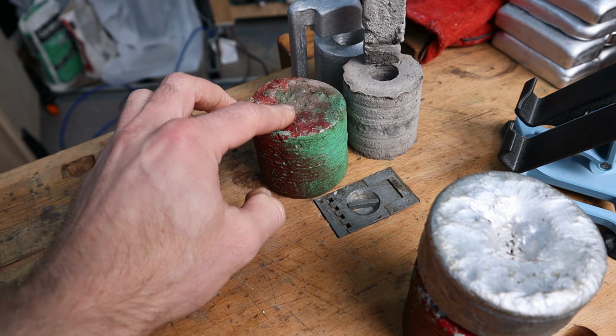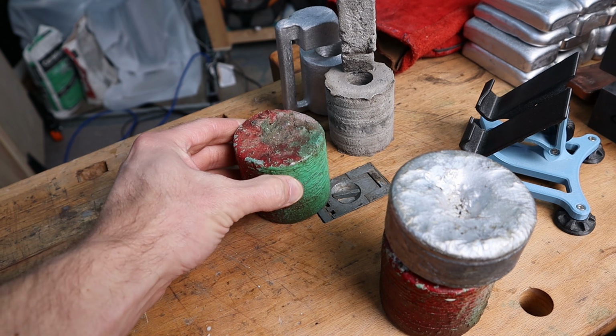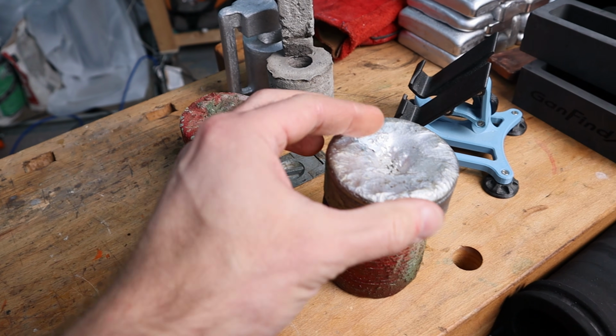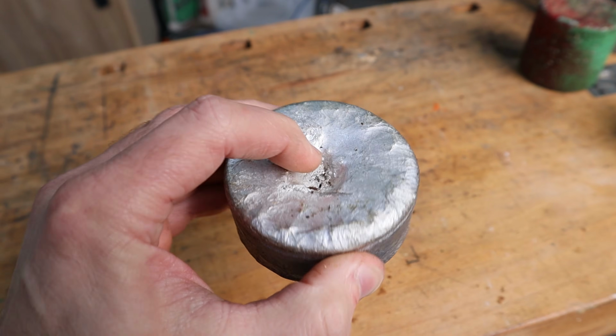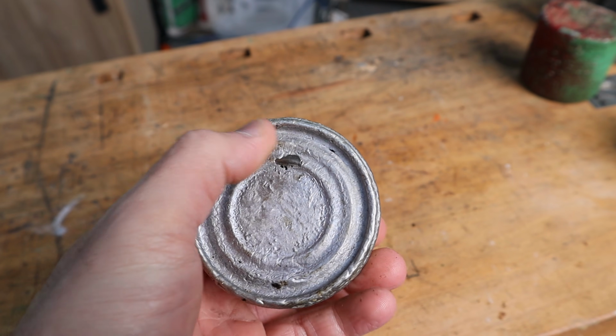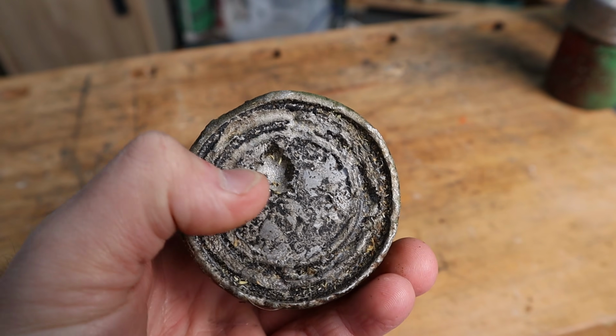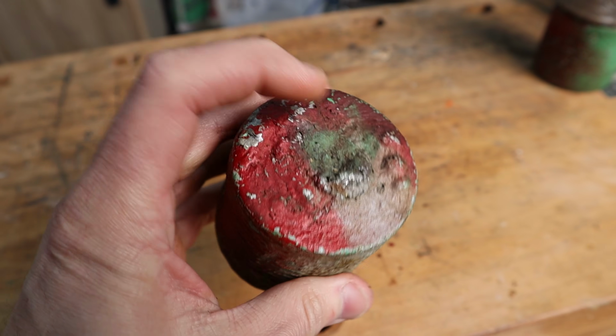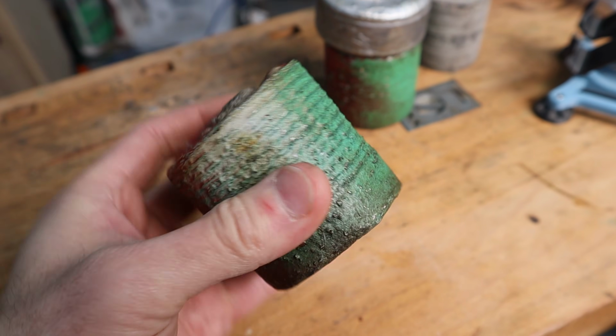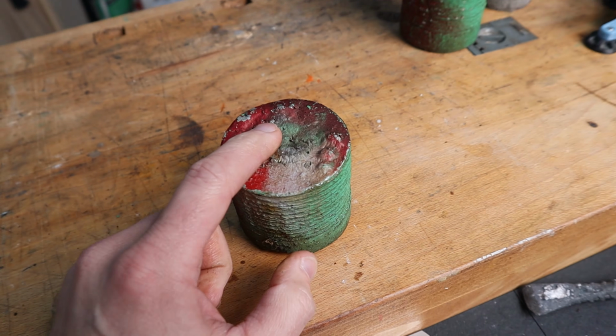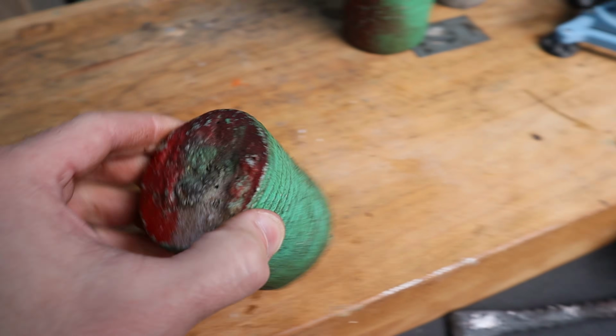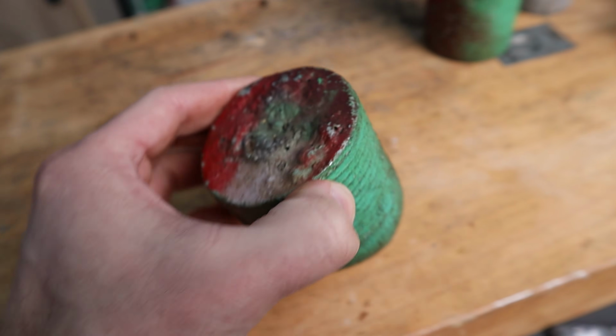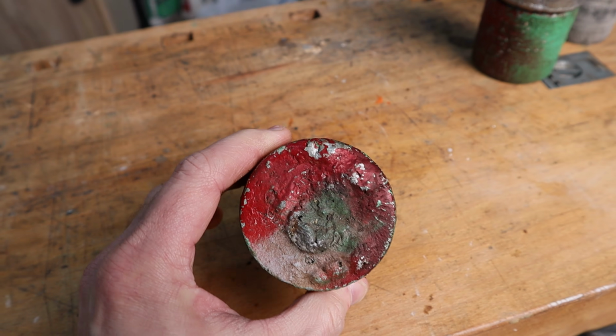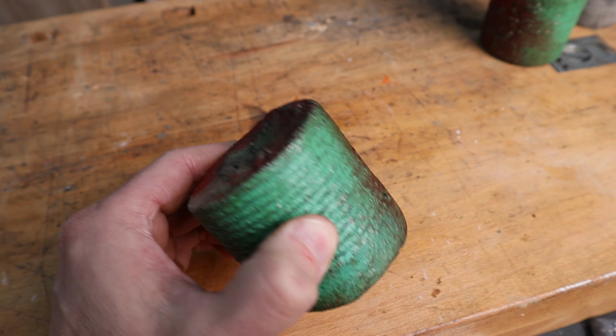So although there's plenty of material there, it would be a lot of work to actually get the final part out of that. This one was a smaller tin, so it's sunk in quite a lot on the top. Some inclusions in there as well. And then we have this one here, same kind of idea. We have these voids in the bottom, a really rough top. So quite a bit of material to remove. Unfortunately, these are a little bit too big to put into the crucible to melt them back down. I didn't really want to cut them back up, so eventually maybe I'll get a larger furnace to be able to melt these down.